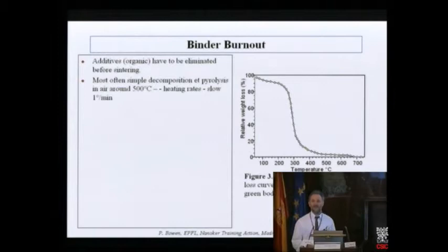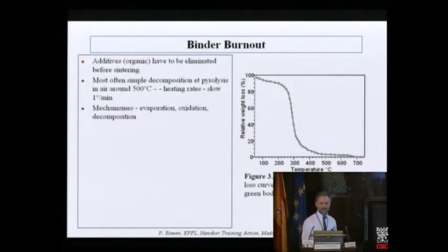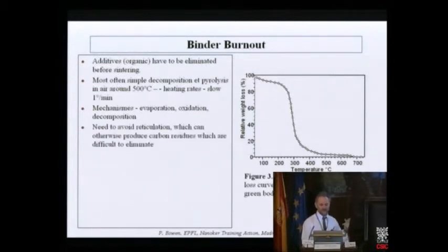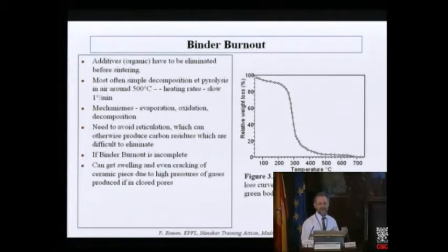Polyacrylic acid is quite nice because it depolymerizes and doesn't leave a carbon residue. So mechanisms can be evaporation, oxidation, or decomposition. You need to avoid reticulation. If you form a carbonaceous material that is difficult to eliminate before sintering, you can actually get swelling and cracking of a ceramic piece due to the high pressures if you start forming carbon dioxide in a closed pore. There are several examples in the literature where you actually get a swelling, an increase in the dilatometry of the particles, due to this incomplete binder burnout.